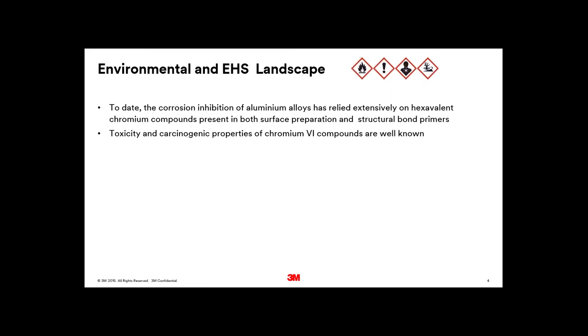The toxicity and carcinogenic properties of chromium 6 compounds are well known. They've been around for a very long time. They are a carcinogen, and they're damaging to the aquatic environment. Most structural bond primers, paint primers, are also solvent solutions, so you've got a very high solvent content, and volatile organic compounds coming off. The other issue is the control of the waste stream of these products, because there are chromium salts in the waste. So they have to have separate waste streams and very special handling. They are a bit of an environmental nightmare